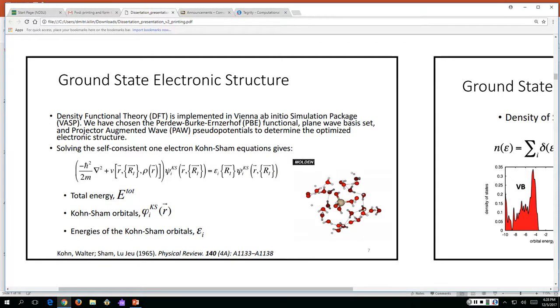So the first thing that's going to happen is we'll find a problem or material that we're interested in, and we'll be able to build a model of it. We'll take this computational model and place specific atoms in an arrangement that simulates the chemical system, and we'll want to optimize this structure. The optimization is a process in which all the atoms are shifted slightly, and an energy is calculated. Every time the atoms are shifted, the energy gets recalculated, and this is done repetitively until the lowest possible energy configuration is found, or until the total energy hits some sort of threshold that we're happy with and we think is close enough to the lowest energy configuration.